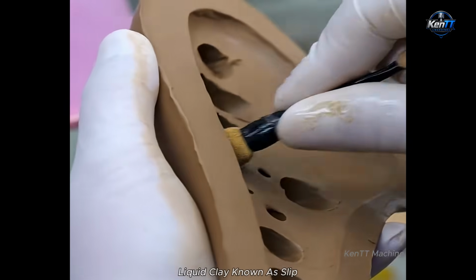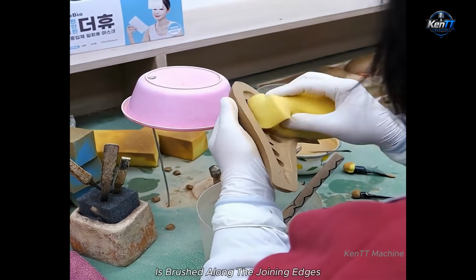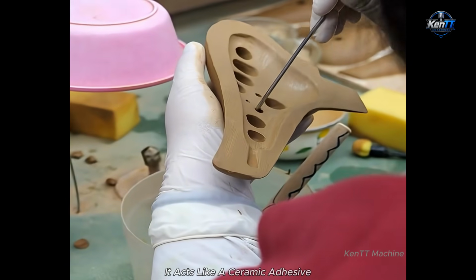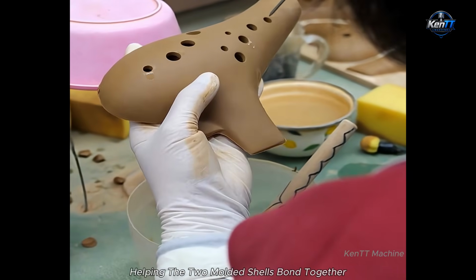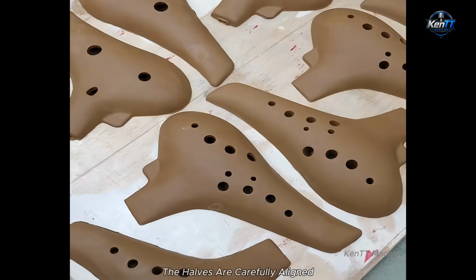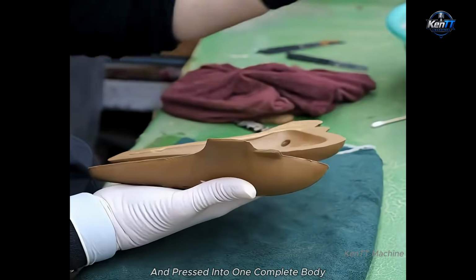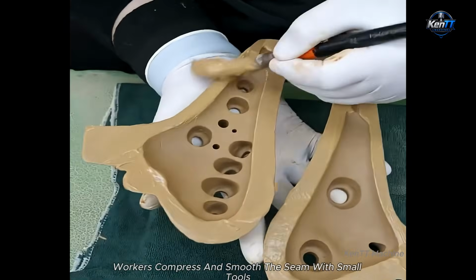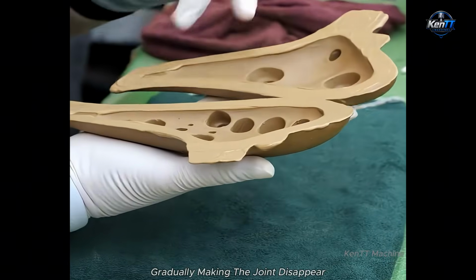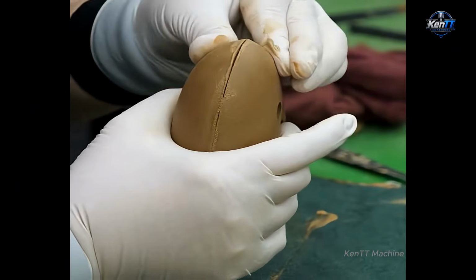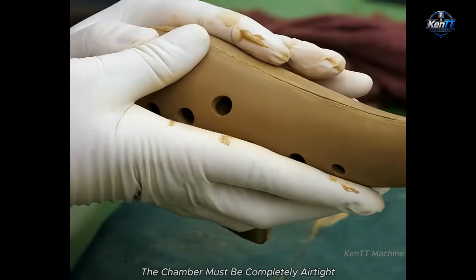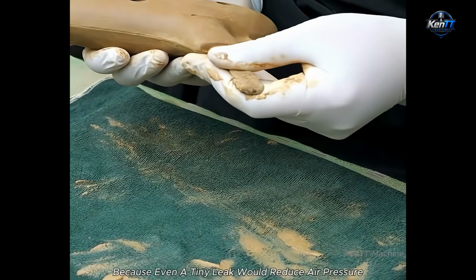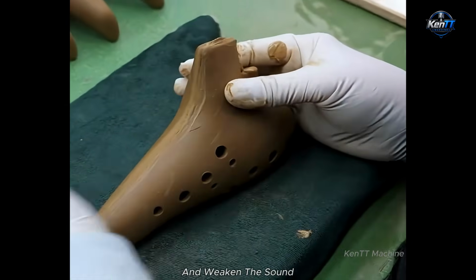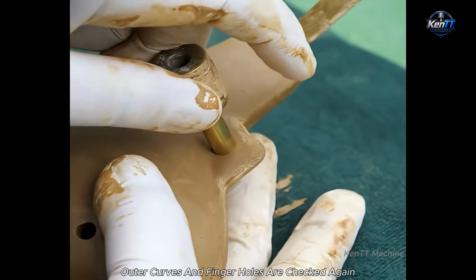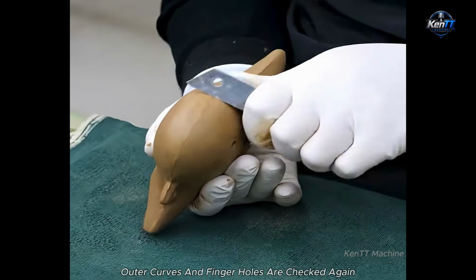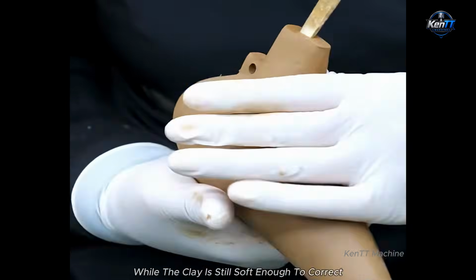Liquid clay, known as slip, is brushed along the joining edges. It acts like a ceramic adhesive, helping the two molded shells bond together. The halves are carefully aligned and pressed into one complete body. Workers compress and smooth the seam with small tools, gradually making the joint disappear. The chamber must be completely airtight because even a tiny leak would reduce air pressure and weaken the sound. The mouthpiece, outer curves and finger holes are checked again, while the clay is still soft enough to correct.